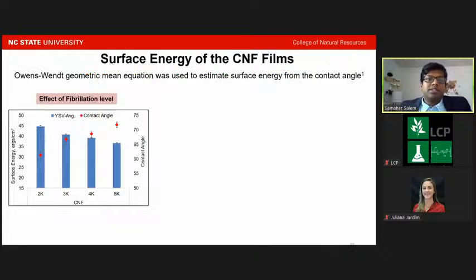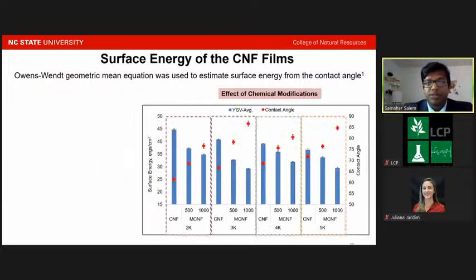So we measured the surface energy of the CNF films using the sessile drop method at room temperature, 23 degrees Celsius. And we also used the Owens-Wendt geometric mean equation to estimate the surface energy from the contact angle. And we could find that the surface energy decreased as the contact angle increased with the fibrillation. We also observed the effect of chemical modification. For each of the nanocellulose samples prepared at each condition, for the modified samples, the surface energy decreased and the contact angle increased.